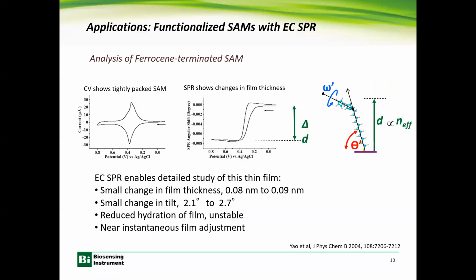So what we're looking at here is self-assembled monolayers on the electrode surface. And the molecule used here is a ferrocene-terminated alkanethiol. And the thiol group is attached to the gold with the ferrocene pointing to the solution. The ferrocene group can be oxidized or reduced by controlling the EC. So the CV shows a very symmetric redox reaction peak here.